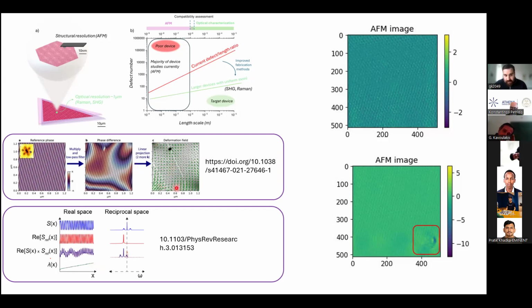And then if you take the derivative of this, you can extract the displacement field. And the displacement field has all the information about the twist angle disorder and the heterostrain that gets introduced between the flakes. And we want to explore this twist angle disorder and the heterostrain in order to aim for a device that is going to be homogeneous on a very large scale.